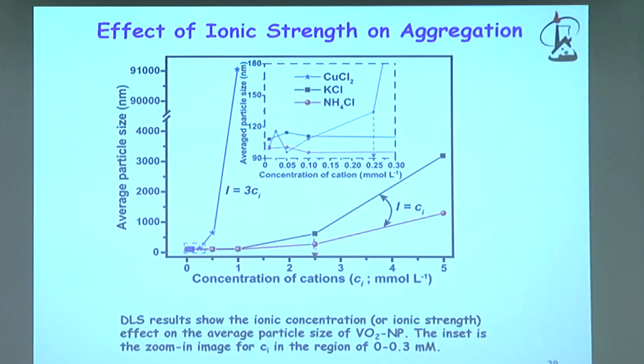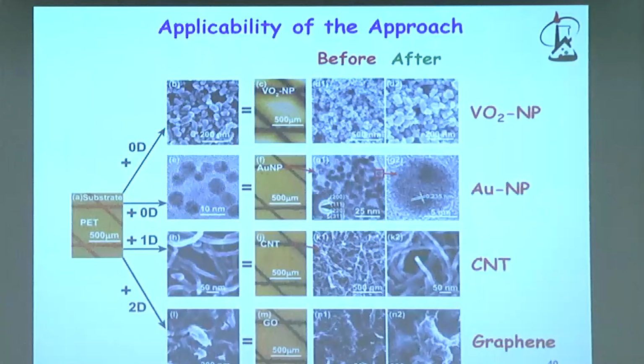Just to show you how this works, for example, this is VO2 nanoparticles. VO2 nanoparticles are thermochromic materials. You can see how the average size of the nanoparticles changes as we increase the concentration of different salts. Obviously, if you use doubly charged salts such as copper chloride, you need a much lower concentration in order to cause the precipitation.